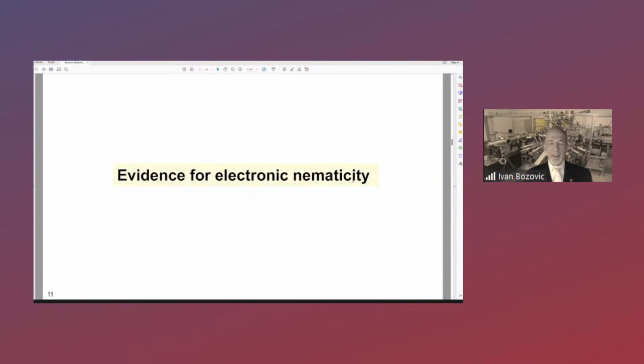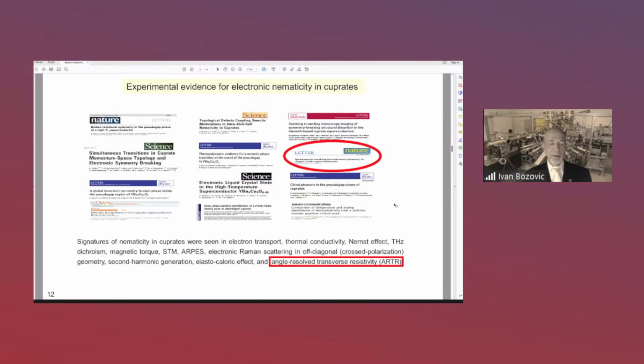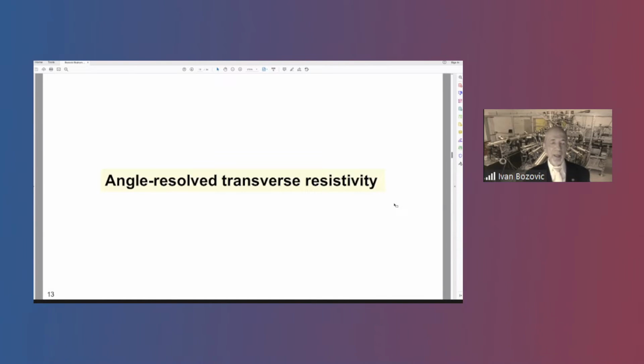Okay, so while ordinary metal cannot be nematic, perhaps a strange metal could. And with this motivation, many experimental groups looked for signatures of electronic nematicity in cuprates and other strongly correlated materials. And lo and behold, when you look for something specific, you will see it. And indeed, many groups reported seeing nematicity in various high-Tc cuprates like YBCO, BSCCO, lanthanum-strontium cuprate, using various techniques. Here, I will focus on only one that I have been directly involved with. We call it angle-resolved measurements of transverse resistivity.